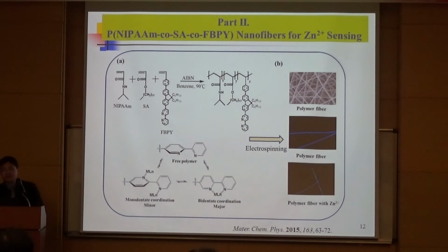So even though in the first part we demonstrated the preparation of fluorescent sensing nanofibers by physically blending the fluorescent sensing compound in the nanofibers, the potential leakage of these fluorophores from the nanofiber may cause a concern in long-term stability. Therefore, in the second part, we look for chemical attachment of fluorescent sensing moieties onto the nanofibers. So here we randomly copolymerize three types of monomers to integrate hydrophilic NIPAAm moieties, physically cross-linkable SA moieties, and the fluorescent sensing FBPy moieties into a random copolymer, then through electrospinning fabricate its corresponding nanofibers for metal sensing studies.